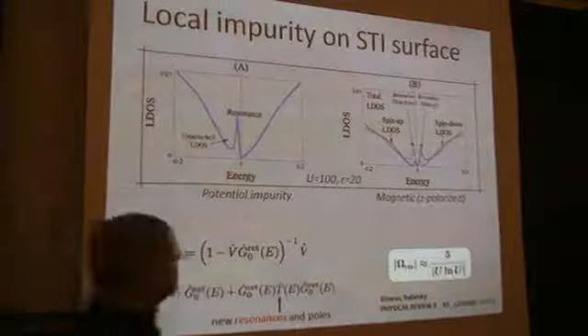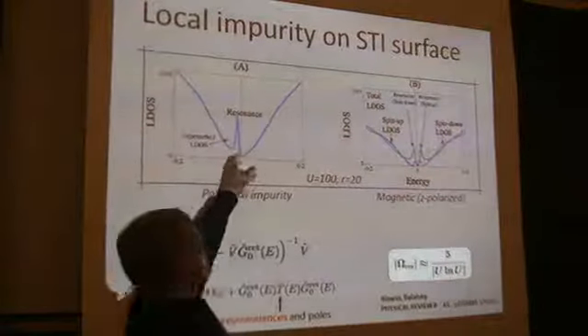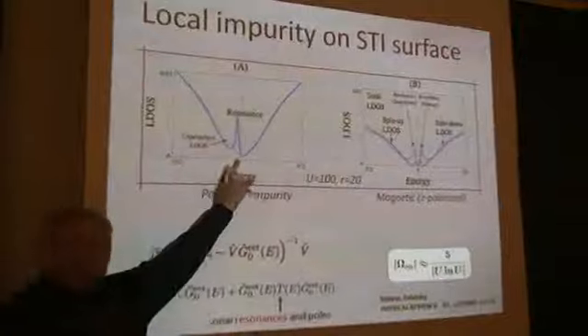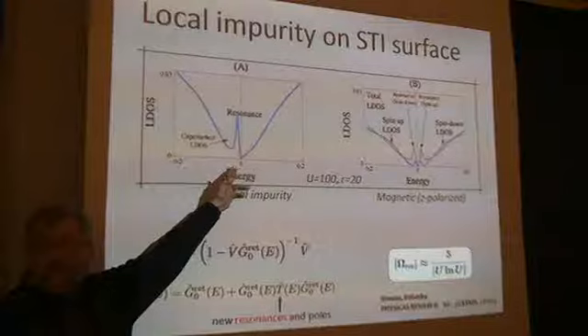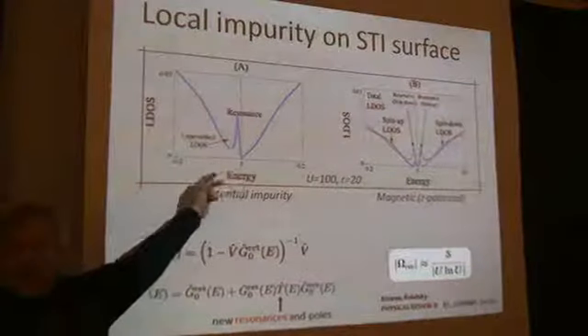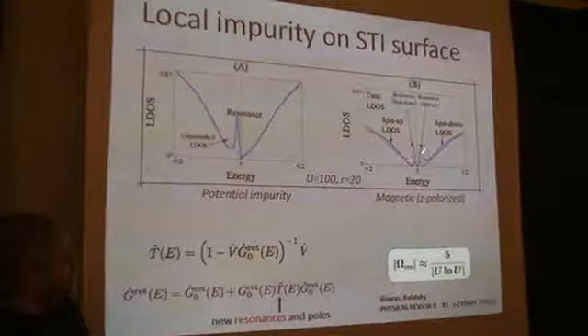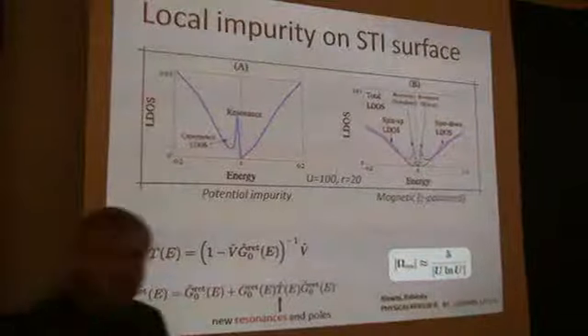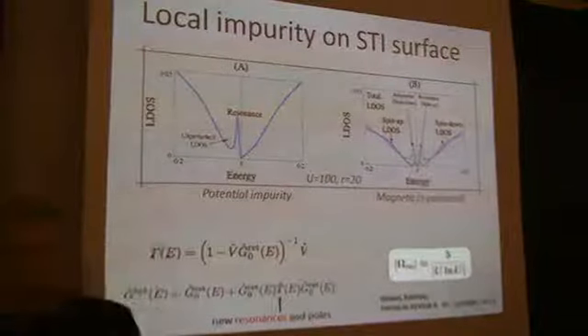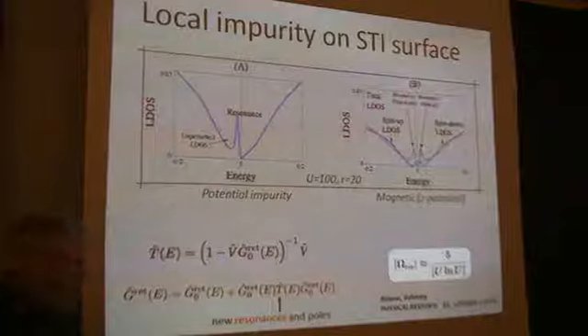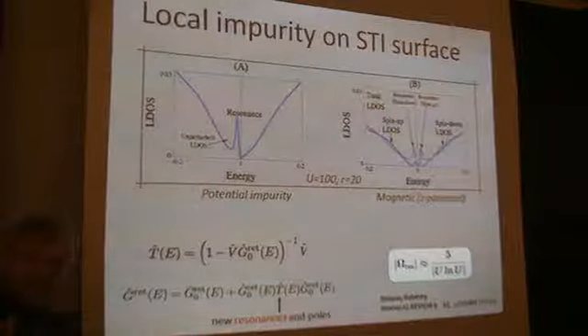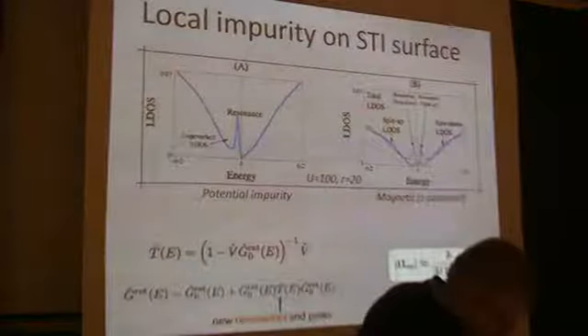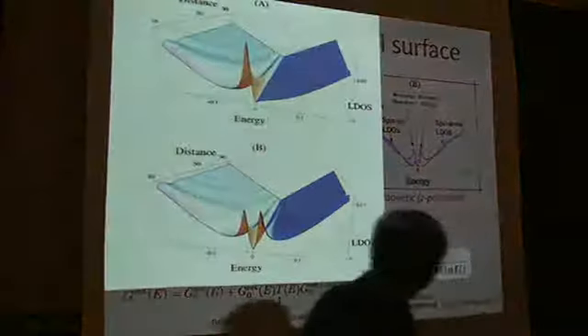And somebody was asking me, even in the presence of spin-orbit coupling, there is still this double degeneracy coming from the combined chirality in the topological insulator. But if you put a magnetic impurity, for instance, it lifts this degeneracy, and there will be two resonances. One of them moves to the left, and one of them moves to the right of the chemical potential. It's similar to what you would guess for the graphene case. If you have a magnetic impurity, you will see it doubly split. What used to be a spin degenerate state will split into two. Yes, the functional dependence of this is the same. It goes like the impurity potential.